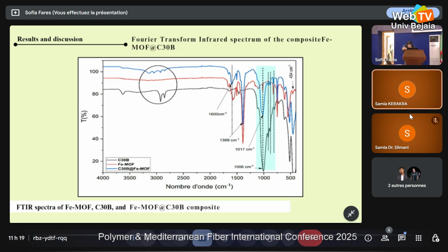Let's continue with the infrared of our composites, MOF and clay. As you can see here, a broad band around 1600 in the clay indicates hydroxyl groups of clay, which shifts in the composites, suggesting interaction between the clay and the MOF via hydrogen bonding or coordination.